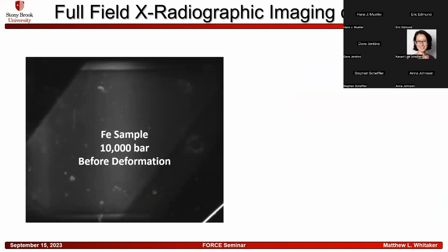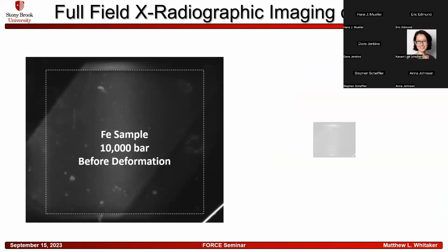And that image is shown here at the left. Just in case you're not used to looking for things like this, this box here shows the outline of what the image is. So I'm going to flash it back and forth a little bit so you can get used to seeing it. The iron part is darker than the surrounding materials, but that is a sample before deformation. We then added a 12% strain field before we did the heating process.